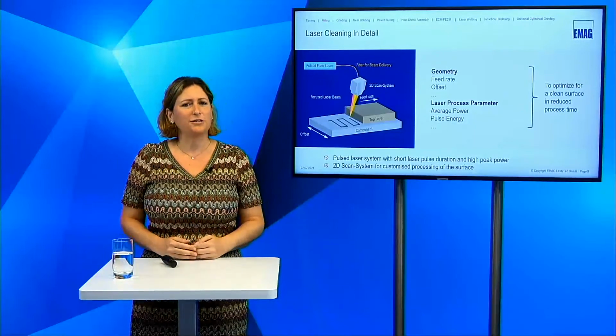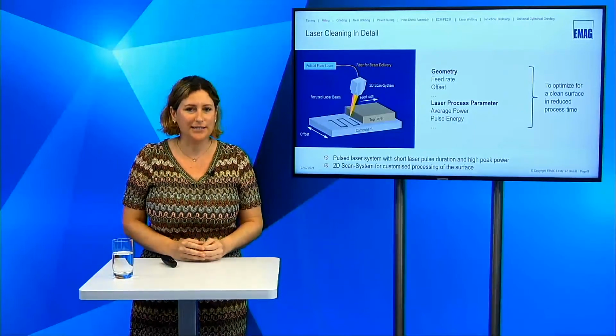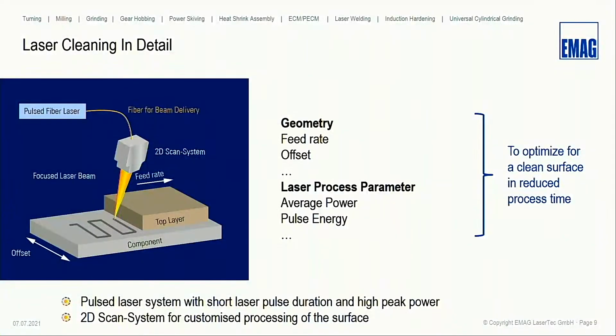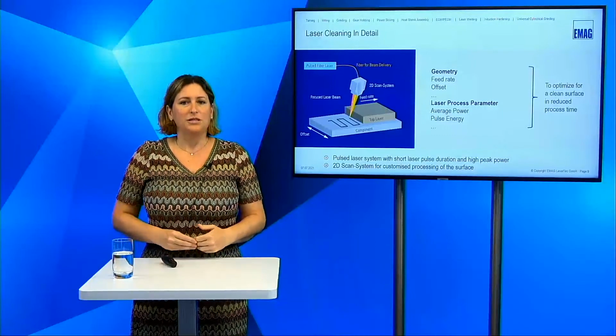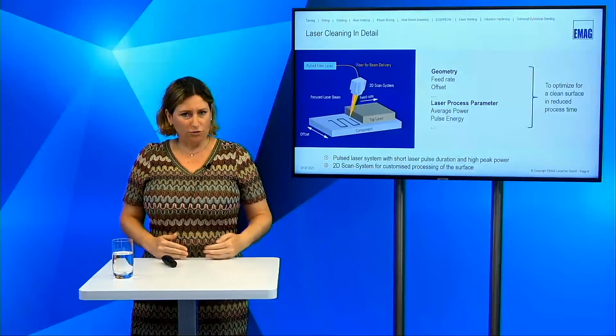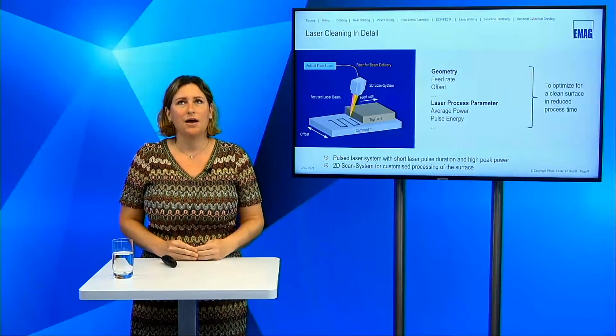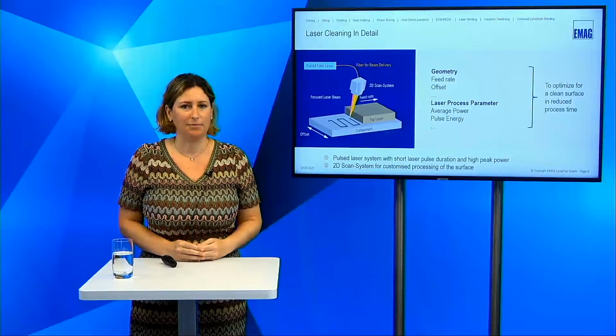The laser beam is created by a laser system, more precisely a pulsed laser system. Why a pulsed laser system? Since you use the pulsed laser with really short pulses, you can generate high peak powers. With the high peak powers, you can remove different kinds of materials quite well. And also the interaction time from laser beam to material is really short, like 1/1,000,000th of a second. This means that the material which you do not want to remove, which should stay the same, will not be really influenced by the laser beam.